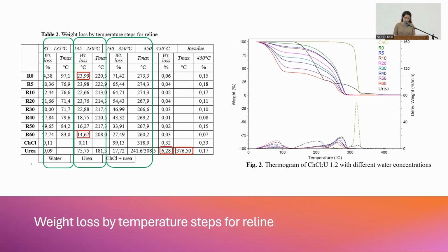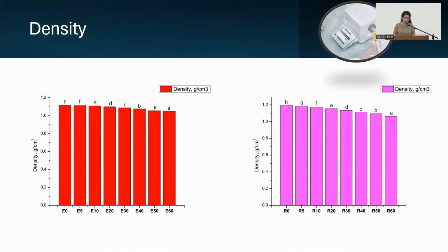In the Reline, we have here 3 steps. Firstly, the water leaves it. Then the urea is more stable, and it also degrades in the third step, also with the choline chloride. Another analysis was the density using a densimeter method from Mettler Toledo. As we can see, the density of both solvents slightly decreased with the increase of water.